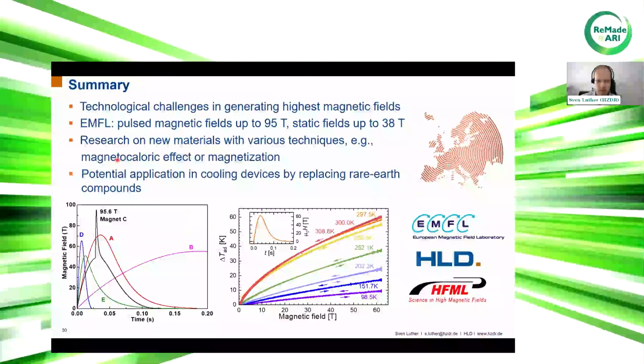Now I'm already at the end of my talk, and I want to summarize what I've shown. To generate the highest magnetic fields, we have certain technological challenges, but by overcoming these challenges in our EMFL facilities, we can generate pulsed magnetic fields up to 95 Tesla and static fields up to 38 Tesla. And by applying these high magnetic fields, we can do research on new materials with various techniques, which I've shown, for example the magnetocaloric effect and the magnetization. These investigations can have potential applications, for example in cooling devices for the future, where we can try to find new materials to replace, for example, rare earth compounds.